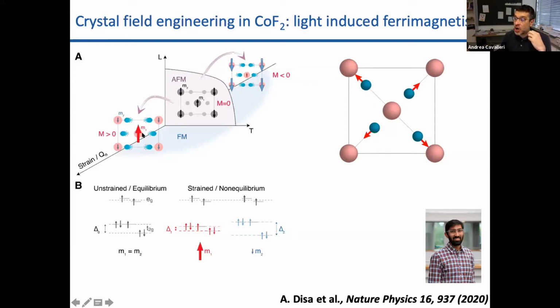And secondly, because these are not strain, but optical phonons, and these distortions happen at constant volume, I can drive distortions that are 3 orders of magnitude larger than the ones that I can drive by strain, because at some point, if I apply pressure on a material, the material will crack. And I can drive changes in the magnetic moment that are 3 orders of magnitude larger than any piezomagnetic effect that was shown. So this was very beautiful work, which was proposed theoretically and was demonstrated by my postdoc, Ankit Disa, who wrote a very beautiful paper that we're all very proud of, and he's just joined the Cornell faculty on the back of this work. So we're all very pleased with this.